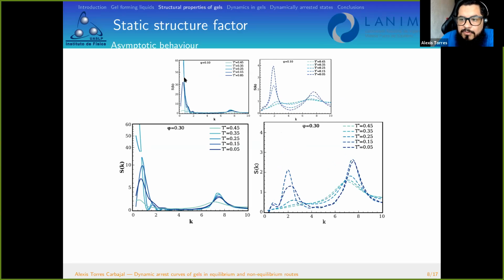Since in the Lennard-Jones fluid, we can observe a full phase separation if the temperature is inside the binodal region. In contrast, the Lennard-Jones with Yukawa tail, with the parameters used in this work, doesn't exhibit any phase coexistence. So we call this an equilibrium route, because at the end we observe an arrested state, but the conditions are different, since in one case we see an interrupted phase separation, and in the other case the system has no phase coexistence.